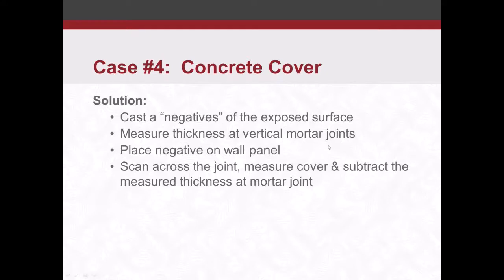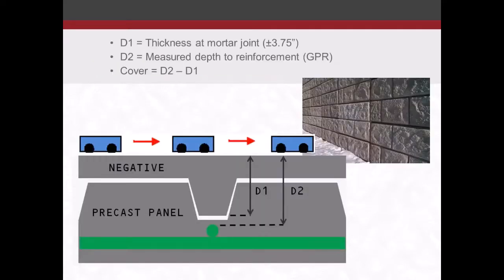We measured the thickness at the vertical mortar joint in our match panel, our negative panel, and we go out to the field and we do our scans. D1, this dimension D1 here, was the thickness at the mortar joint. This was the panel that we cast here over the joint. This is that mortar joint right here. D2 is the measured depth to the reinforcement. That's what we get with our GPR. That's this distance here. And then we just simply take D2 minus D1, and that gives us our coverage.